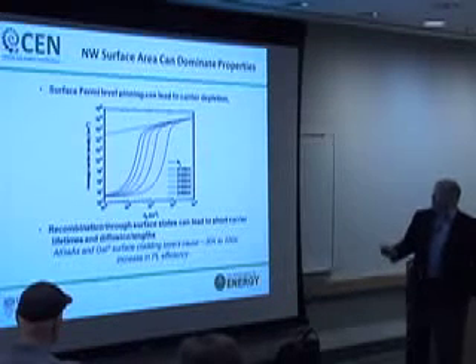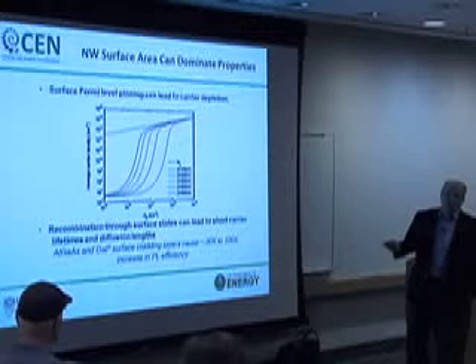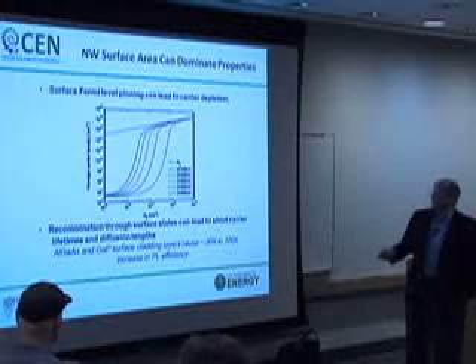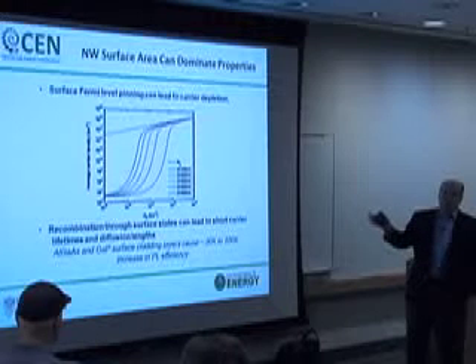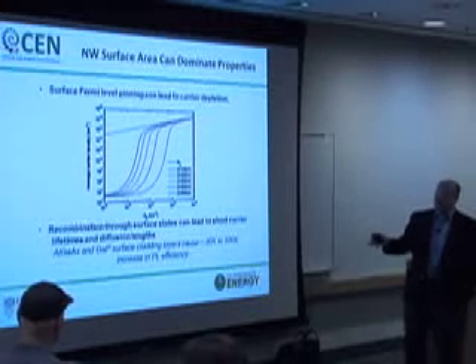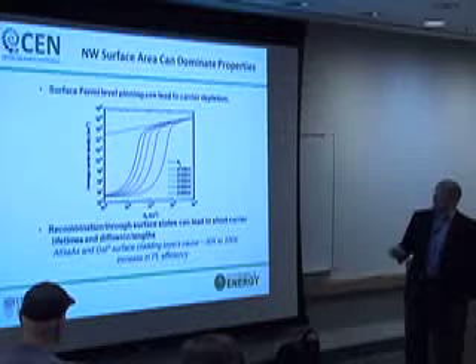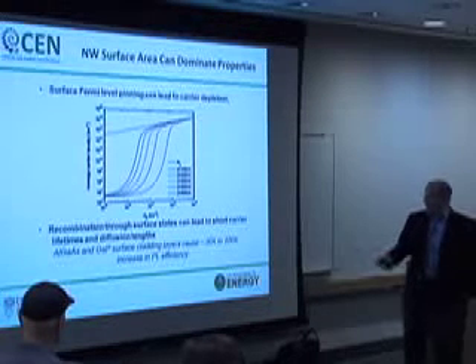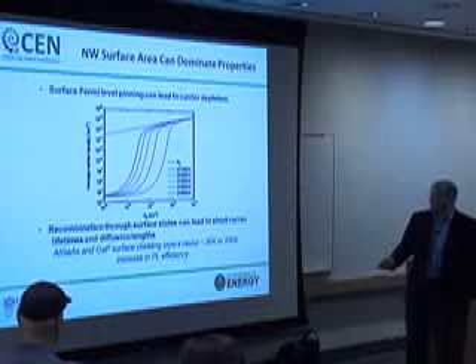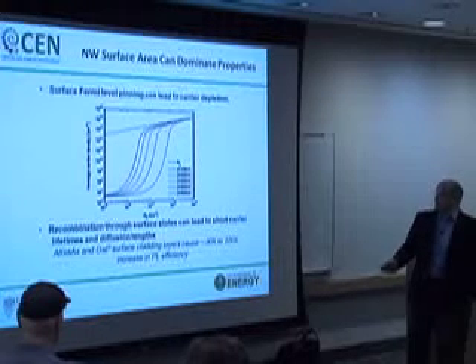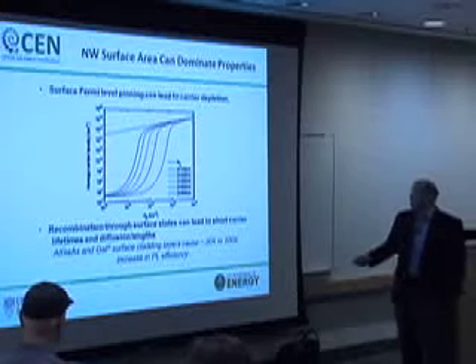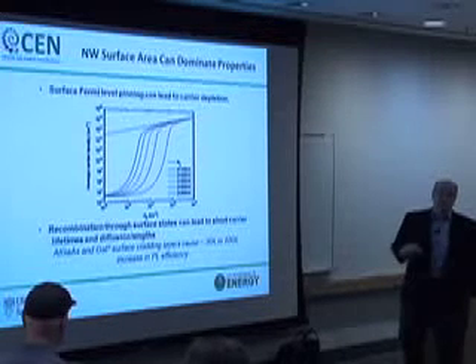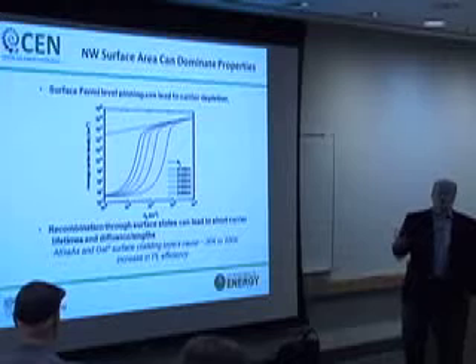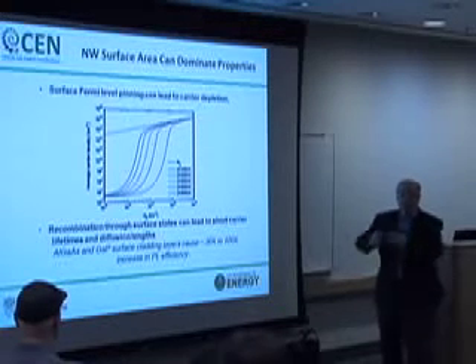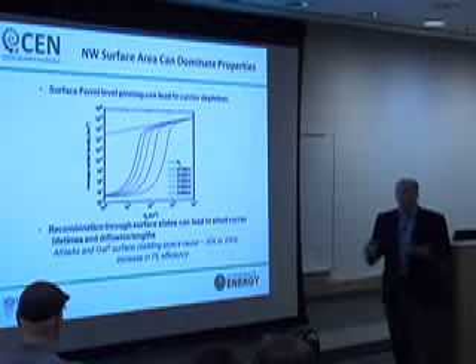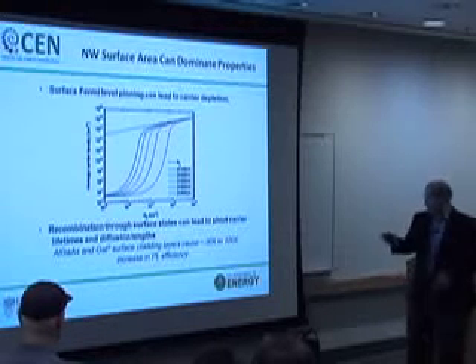The other problem, of course, is that the surface recombination velocity on these materials is very high. We've measured very short lifetimes and diffusion lengths in these structures that are consistent with that. So we've really got to passivate the surface with either AlGaAs or some other large band gap material. When we do and look at the PL, we get a 30 to 100 times increase in the PL efficiency of the material, indicating that we're reducing the amount of surface recombination. Whether it's enough to make a good solar cell or not remains to be seen.